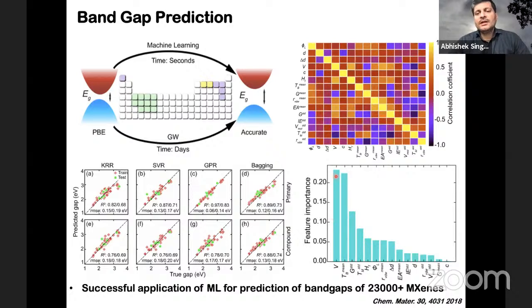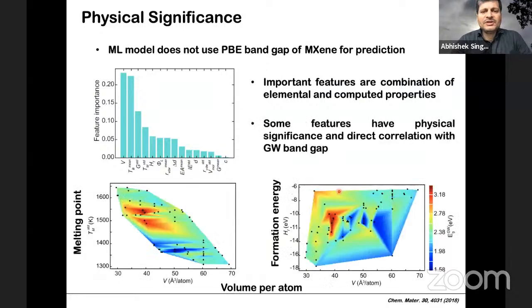We also looked at, as a byproduct of the actual model, the important features. Which features played the most important role in the prediction? In this case, we found, for example, volume. Sometimes you can derive the underlying physics from these features, why a certain feature has more importance, and very many times you'll find that it aligns with your intuitions or what you expected. In the interest of time, I'll not go into the details, but one example which I keep telling is volume. If you have a compound or a MXene which has a larger volume, naturally it will have a lower band gap.